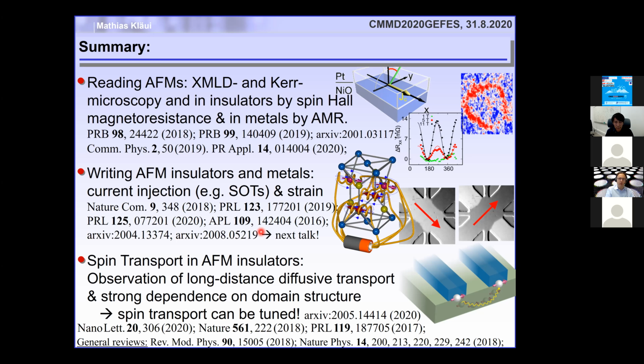And one of the things that we've been looking at, for instance, is this thermally excited domain wall motion. There's all this theory work from Uli Nowak, who's done some really nice predictions that domain walls should move in a thermal gradient, but that somehow turns out to be not so easy to see with high confidence. We have some indications that this exists, but it's tough because of these inhomogeneities which lead to pinning sites and so on. So I think fundamentally this effect should occur, but we haven't seen it yet. That's probably the closest answer I can give to you.